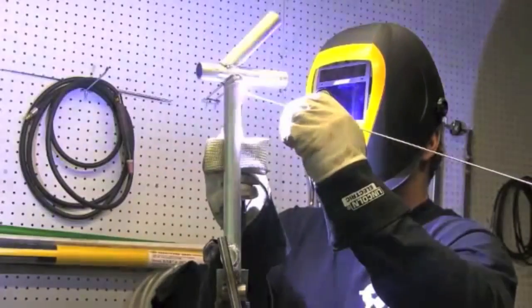Also on aluminum, heat input affects the properties of the metal a lot. Typically when you overheat aluminum, you're going to basically take it back to its annealed stage, which is the softest stage in a certain area right around the weld. That's why a lot of people will set up pulse parameters for aluminum to limit the heat input.